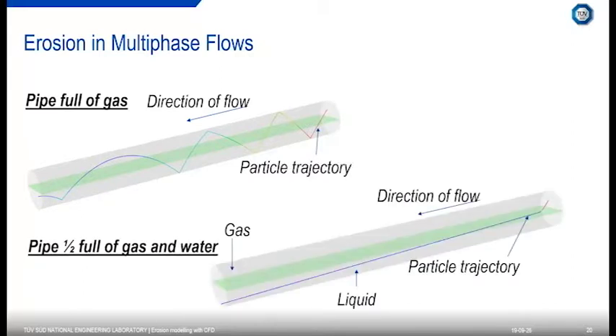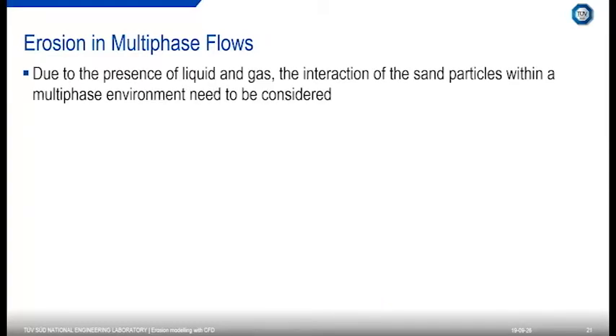If we now consider what happens when the top half is full of gas and the bottom half is full of water, what we will have is the particle again comes in at, say, 2 meters a second at a 45 degree angle. This time it doesn't bounce off the wall. It loses all its inertia, so it continues within, it gets trapped within the liquid. So therefore, in multiphase flows, a liquid film could develop, which actually could, in this case, help reduce wear. However, that's not always the situation. It helps sometimes, but it's not always the situation. So we do need to consider the interaction of the sand particles within a multiphase environment quite carefully.